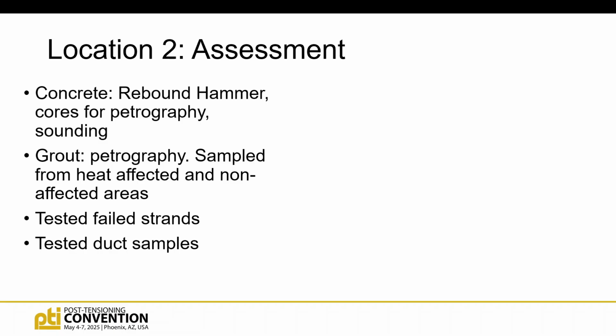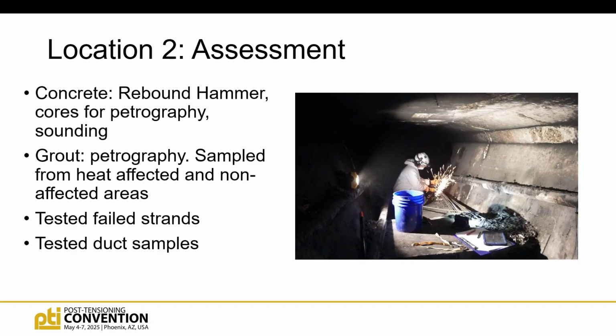For the grout, we took some samples. We'll do some petrography once again in the lab, looking for the degree and depth of heat effect on that grout, so we can determine which strands might be more greatly affected by the heat. We removed some strands and tested them to failure to understand the properties of those strands. And we also tested some duct samples in an attempt to correlate duct condition to the heat that the tendon saw. And all of this was geared towards how hot did the strands get and can they stay in place? That was the ultimate question we were asked to provide. So there we are, that's Lane, my technician, cutting strands.